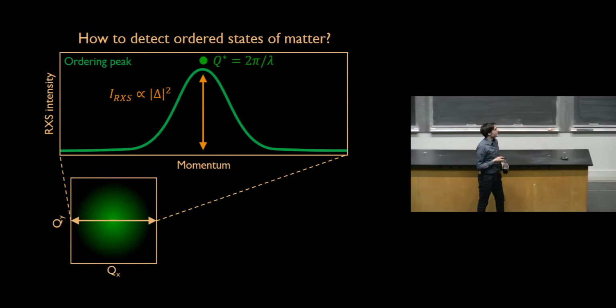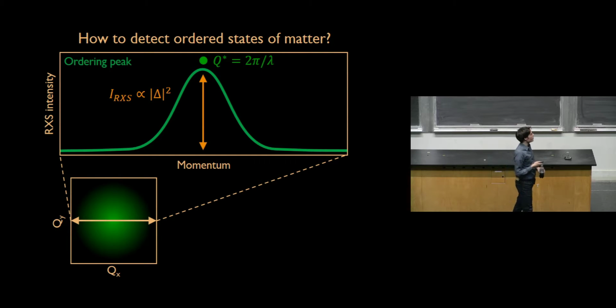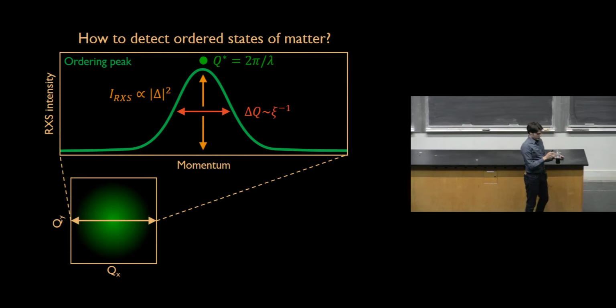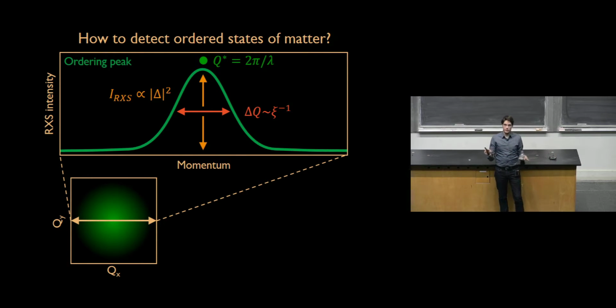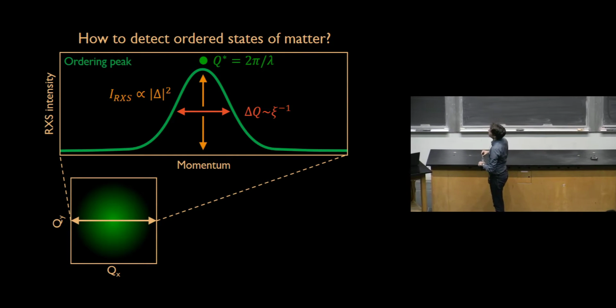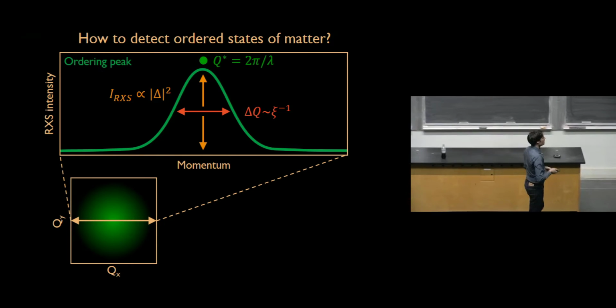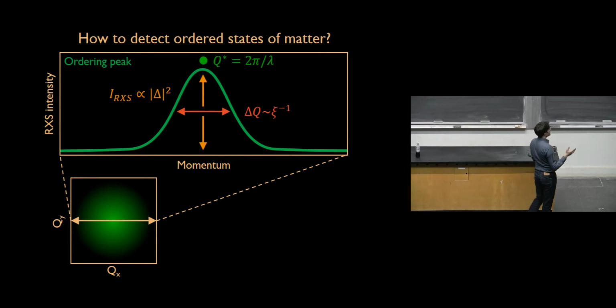The height, or the amplitude, is proportional to the square of the order parameter. So how strong is your order? The width is proportional to the length scale of your order. So is it long-ranged? Is it short-ranged? The sharper the peak in momentum space, the more long-range your order will be, because of the inverse relationship between momentum space and real space when it comes to broadening, right? Delta Q times delta R is a constant.